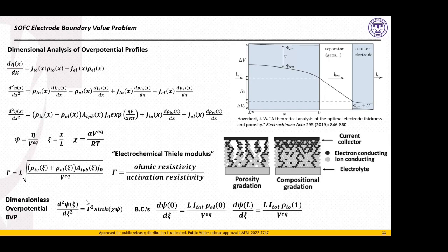overpotential in limiting scenarios. What's important for us to notice briefly here is that this term here is essentially the ohmic resistivity divided by the activation resistivity. And a couple of authors have denoted this as the electrochemical Thiele modulus, which is a modulus that is oftentimes used in catalysis to measure how effective a catalyst, a reactor, is. And what we'll find throughout this optimization is that, generally speaking, SOFCs are poor catalytic reactors. They do a poor job at being catalytic reactors.